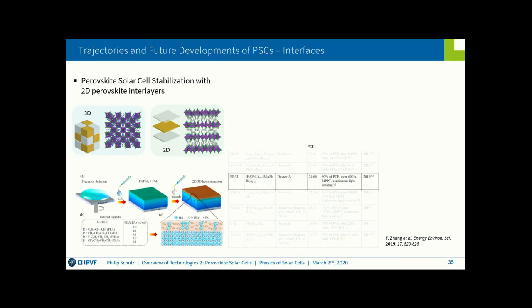And okay, so why not show a table with hundreds of numbers? Only pay attention to this one here, where PEAI has been used in order to make a 24.65% cell with 90% power conversion efficiency still achieved after 600 hours at max power point with continuous light soaking, just in order to give you an example.